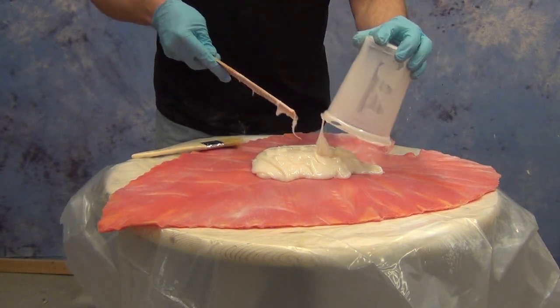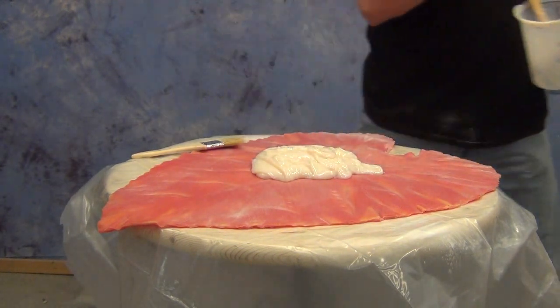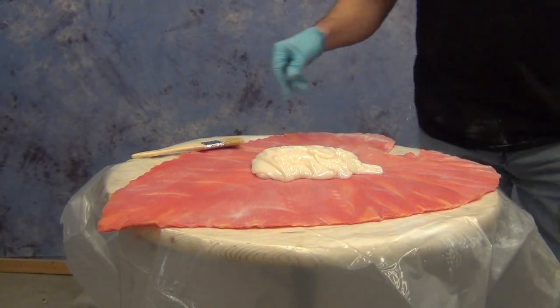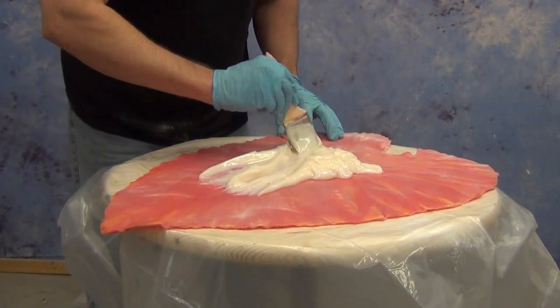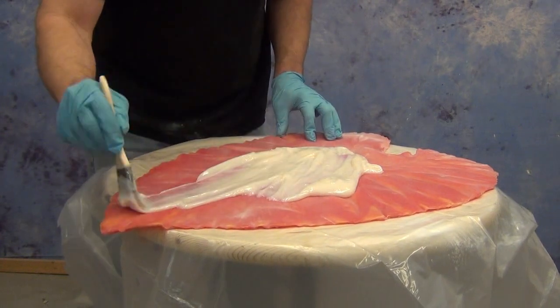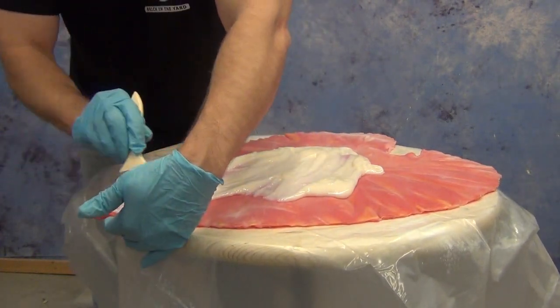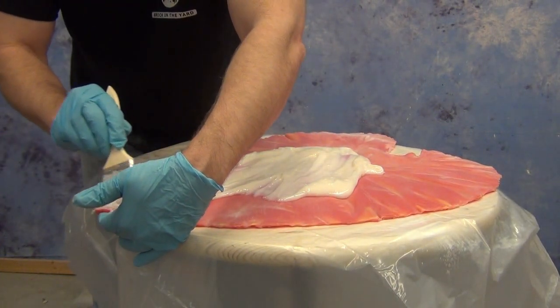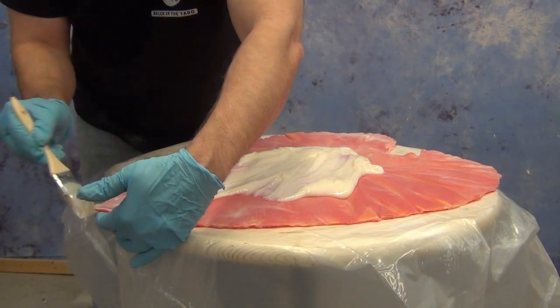Now, one of the things I always like to do when I'm mixing up a resin system like this and for a brush-on application is I like to get it out of the mixing cup and spread out as soon as I can. The reason for that is when it's in a thick mass, it generates more heat, and that's going to diminish the working time. So make sure you get it spread out as soon as you can so you get as much of that working time as possible.